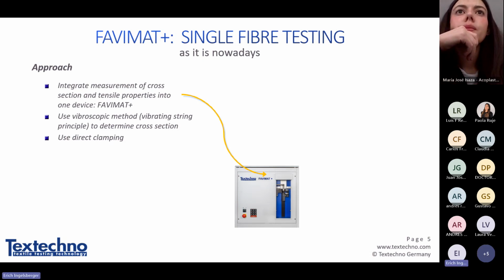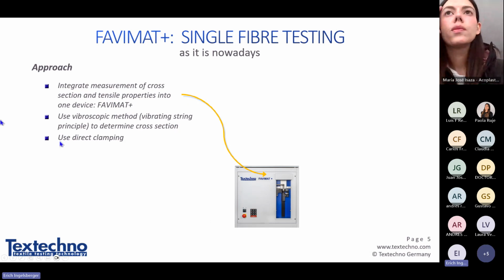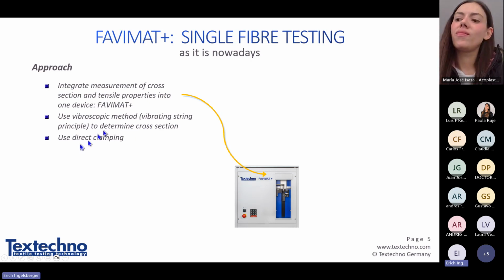Here, we do not need such a paper frame to glue the fiber into, and we can measure the cross section and the tensile properties within one testing instrument. No need to use two different testing instruments. We are using a so-called vibroscopic test method, which I'll explain in a second, to measure the cross section. And we use direct clamping. We do not need these paper tabs. We directly clamp the fiber individually.